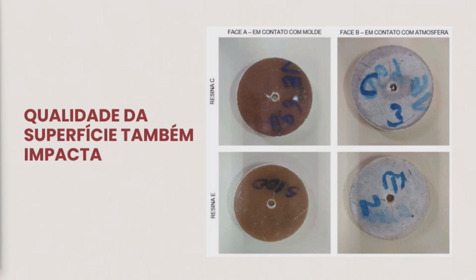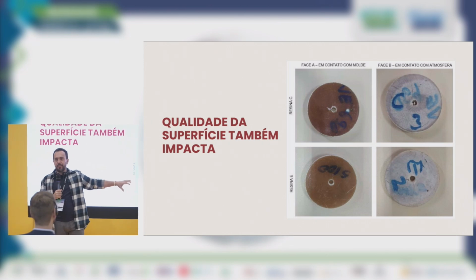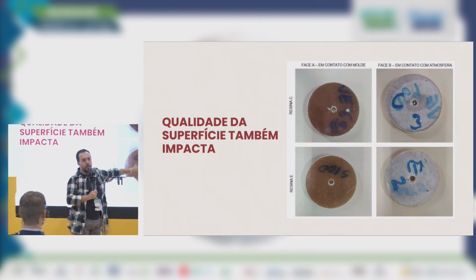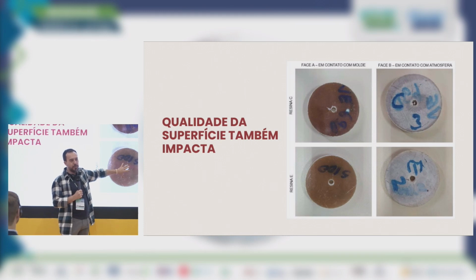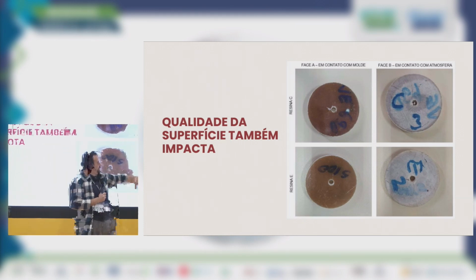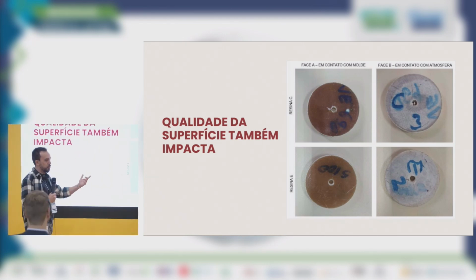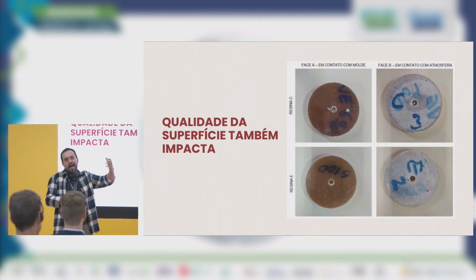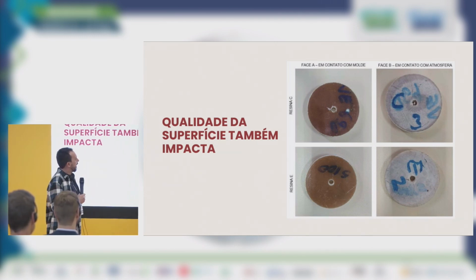One of the interesting findings: the water comes in through porousness or porosity. This one was completely submerged in water, but the surface that was in contact with the mold did not change color. The surface that was in contact with the atmosphere, which is more porous, changed color. So where it's white, then it's water reacting with the resin.